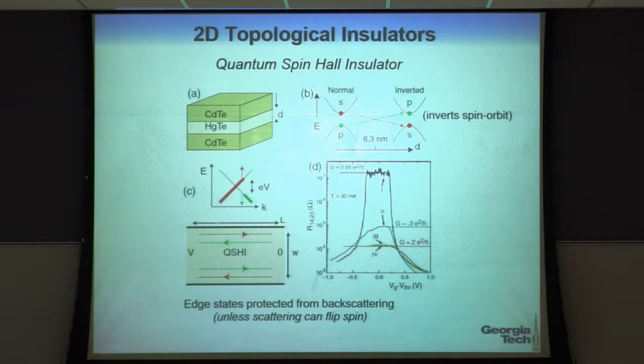And again, I get then a dissipationless edge state, and I get the same for the opposite spin. But now I've got two on one edge. Okay? And so if you look at the quantized resistance of this thing, quantized conductance, it becomes 2 times e squared over h, because I have, going in one direction, 2 modes. They're on opposite sides of the sample, but I have 2 modes. Okay?